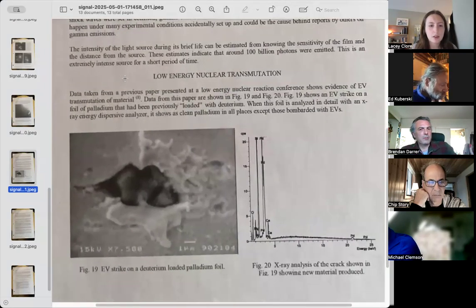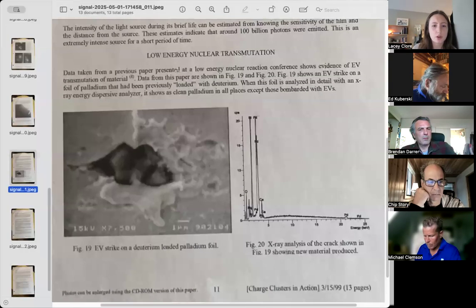In other experiments using double EV structures, where shock waves were set in collision, gamma emissions were measured. This is a common occurrence that could happen under many experimental conditions accidentally set up and could be the cause behind reports by others on gamma emissions. The intensity of the light source during its brief life can be estimated from knowing the sensitivity of the film and the distance from the source. These estimates indicate that around 100 billion photons were emitted. This is an extremely intense source for a short period of time.